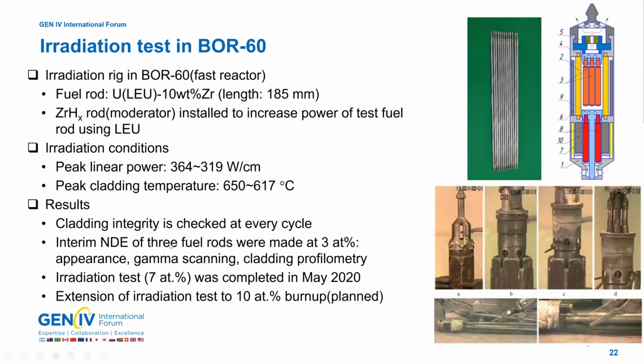So during this, the test reached in May 2020 about 7 at%, and there were some interim non-destructive examinations of this rod, like appearance, gamma scanning, and cladding profilometry to measure the cladding diameters. We have planned to extend this irradiation up to 10, so we are waiting for our government approval for this extension.